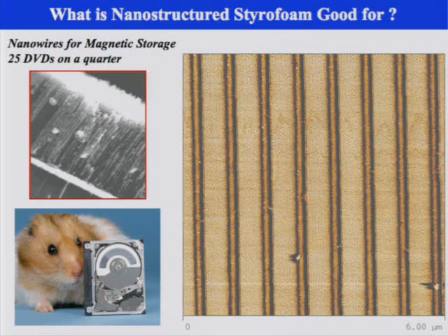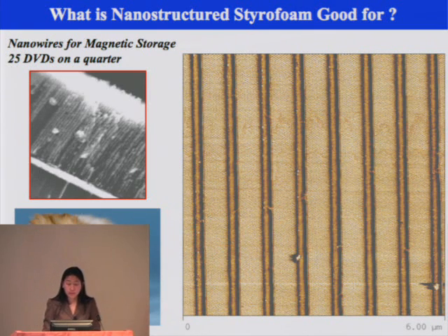In this case, you can see this is a 6 micron scan, and you see there is certain registry in between different rows. If you do a Fourier transform of this AFM image, you essentially get hexagonal packed spots, indicating that the whole image is essentially one grain. This was good, and actually,